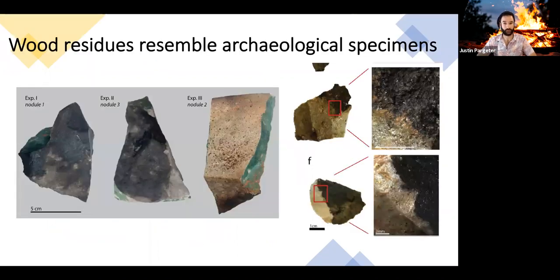Importantly, our experiments also showed a black tempering residue on the surface of all the heated samples. These residues resemble those found on the surface of archaeological silcrete flakes from Diepkloof rock shelter, supporting the hypothesis that they were also heated using surface fires.